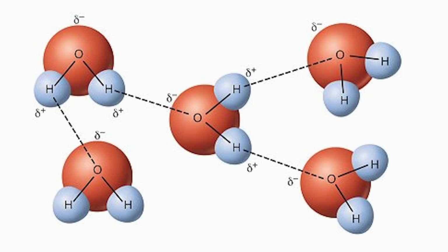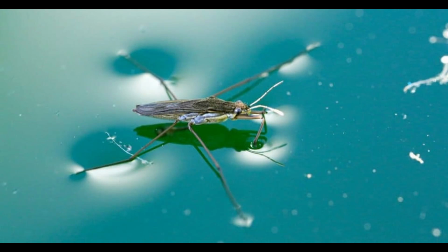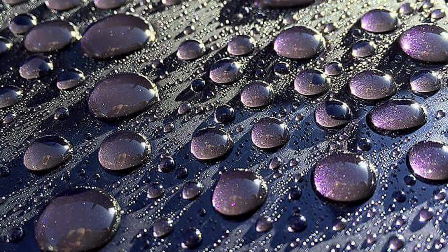As well as this polar nature, hydrogen atoms bound directly to certain atoms, oxygen being one of them, can form what are known as hydrogen bonds. Without getting too sciencey, this effectively makes water sticky to itself and is responsible for its many unusual properties, including its very high surface tension. This allows things like water boatmen to skate around on it, and, importantly for us and our paint, it also allows it to bead up. This is not something we particularly desire in our paints. High surface tension is in fact our enemy.